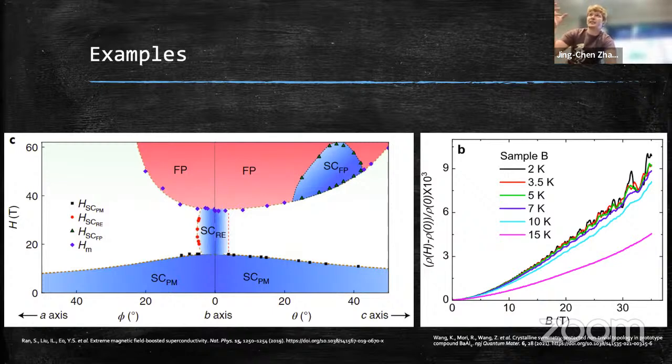Basically, when you have a particle in a magnetic field, it's going to start doing like a helical shape, right? There's quantized energy levels that are accessible. So in a material, when you're sweeping your magnetic field, your Landau levels start crossing the Fermi level, and there will be oscillations on your Fermi surface. So there's oscillations in the density of states. If there's oscillations in the density of states, you're going to see that in magnetic susceptibility or electrical resistivity.